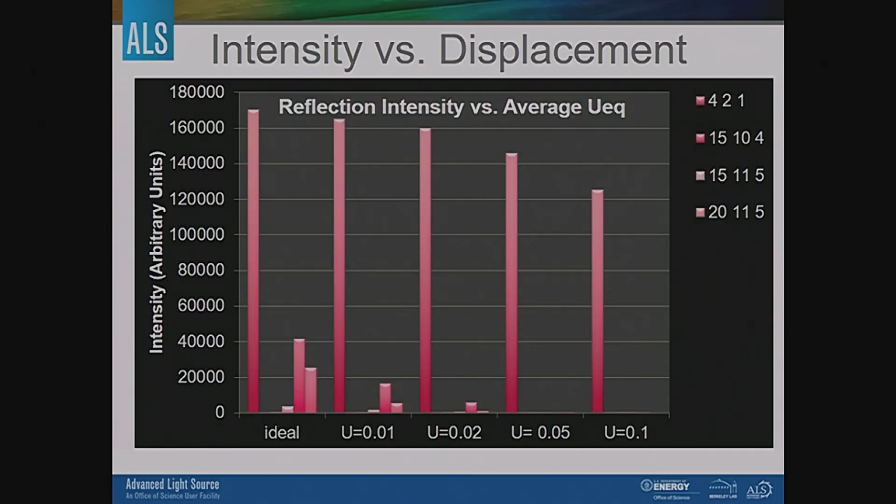This is pretty normal. I would say getting a structure with U's of 0.02 to 0.03, okay, that's good. That's very typical for a good low temperature structure. This I would consider a little wobbly, but not bad. And this I would consider everything's doing this. It's never good when you see anything that has an average U value of 0.1.